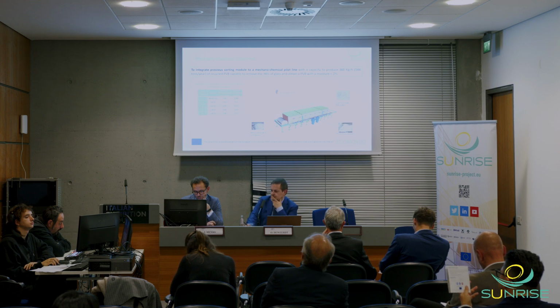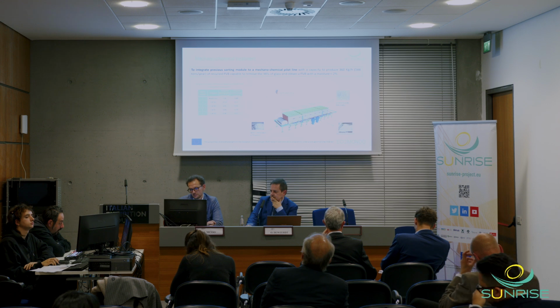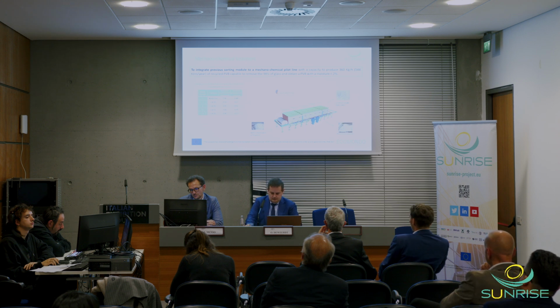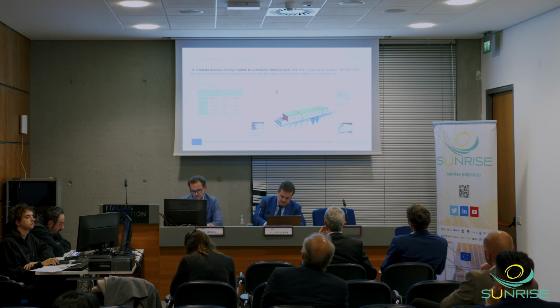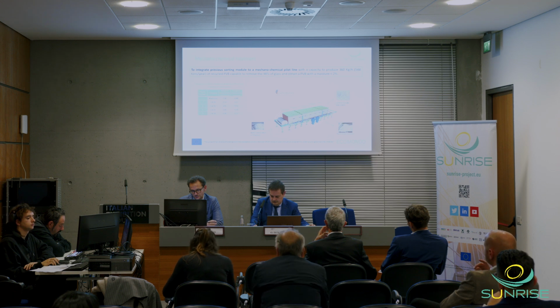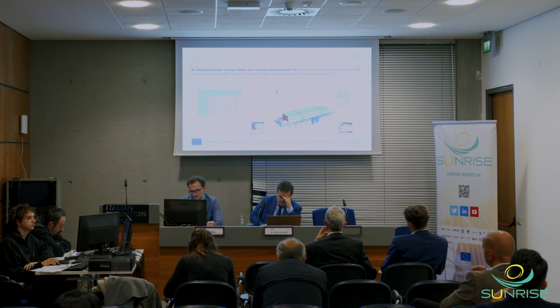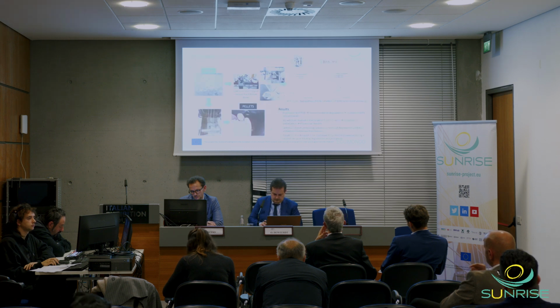So here in the project, these are some examples of batches we have treated of sorted categories. For the case of the high quality category, category 1B in this case, which was triethylene glycol oligoester plasticizer, these are results about the inorganic contents, basically glass, after the mechanical treatment and, more importantly, after the chemical treatment. So we are mostly below 0.5% of glass in the final PVB flakes. So this is regarding the first part of the project.